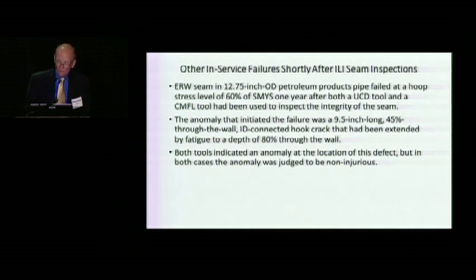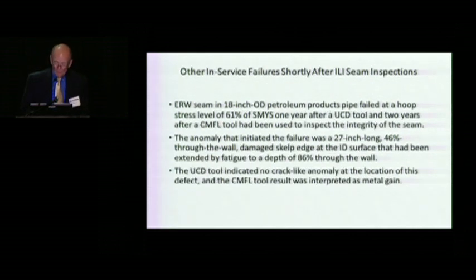Both of the tools had indicated an anomaly at the location, but neither one was judged to be injurious. And I think you'll see some of the reasons for this kind of thing as I go through here. Another service failure was an 18-inch petroleum products line in which the same thing kind of happened. Both types of tools were run, and then a short time later, a very large defect failed in service.